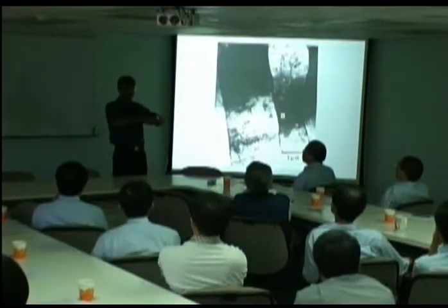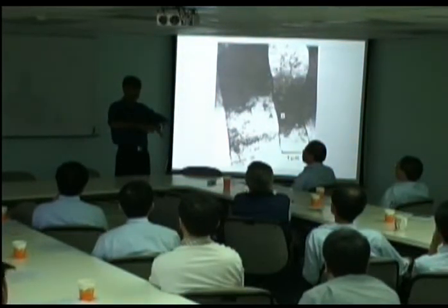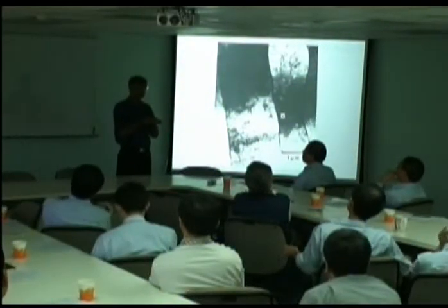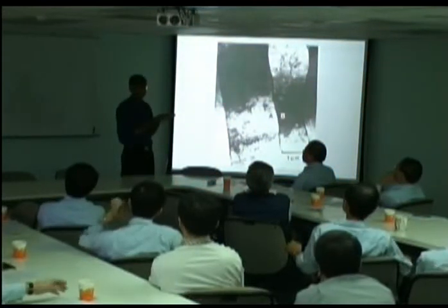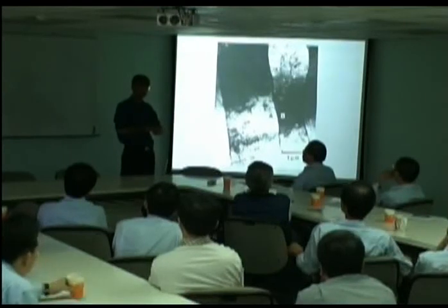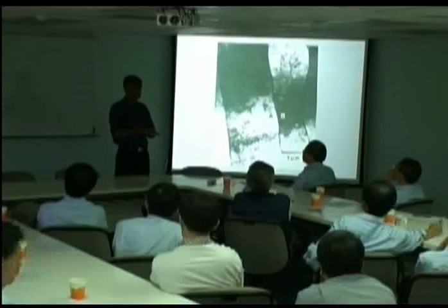Now, why doesn't martensite form like that? Why doesn't bainite form like that and cancel out the strain energy? Well, there is a cost. You have to nucleate those two plates at the same time. And that's why the structure that you get in Widmanstätten ferrite is coarser. You will get a lower nucleation rate because you have to have the right two variants nucleating at the same time.